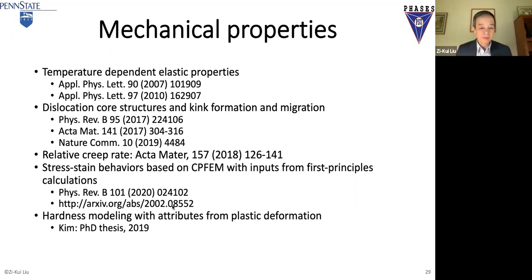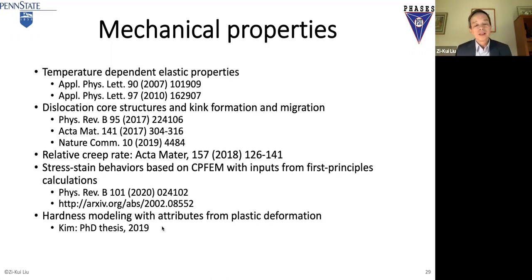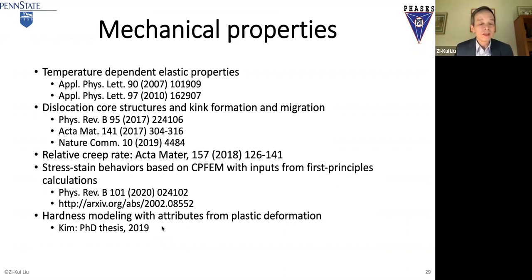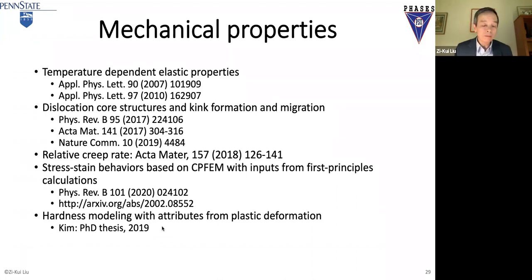More recently, working with my colleague Professor Allison Beese in our department — an expert in crystal plasticity simulation — we can take first-principles input for ideal shear strength and predict the stress-strain curve of single-crystal nickel as a function of orientation. We are also modeling hardness: most hardness models in the literature use purely elastic parameters as input, but hardness is about plastic deformation. My former student Hong Yun Kim developed a hardness model incorporating attributes from both plastic and elastic deformation, which can predict hardness from pure aluminum all the way to diamond with one equation.